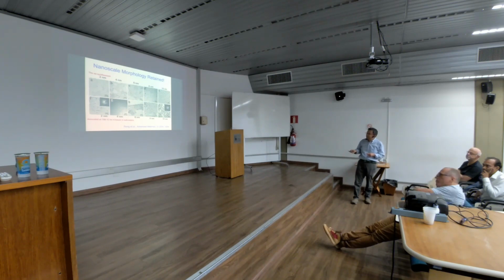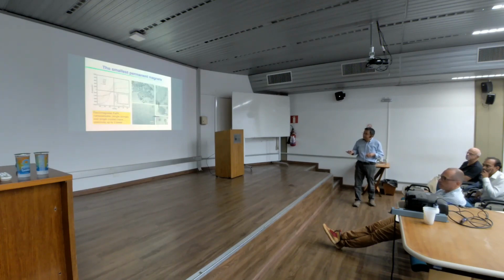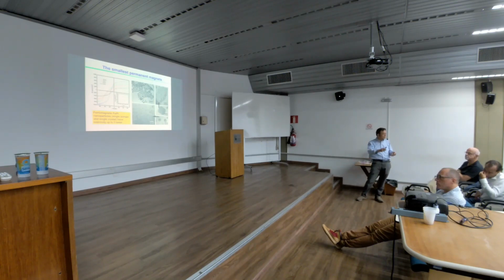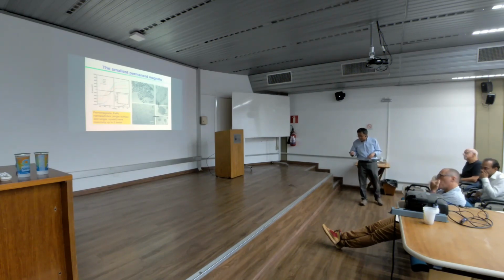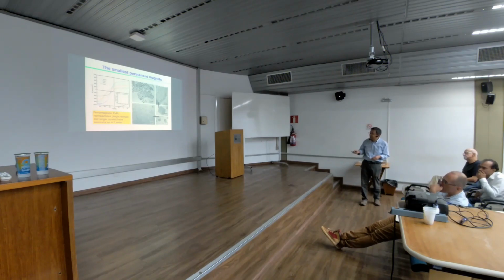They're still monodisperse. In order to know if the phase transition has happened, you can do XRD, you can do magnetic measurement, of course. The magnetic measurement shows that these particles have very high coercivity, up to 3 Tesla. So I call this the smallest ferromagnet. No one can go even smaller. Why? Because then you will reach the superparamagnetic limit. And this treatment method can still keep the shape of the nanoparticles after the long heat treatment, at a temperature of 700 C.